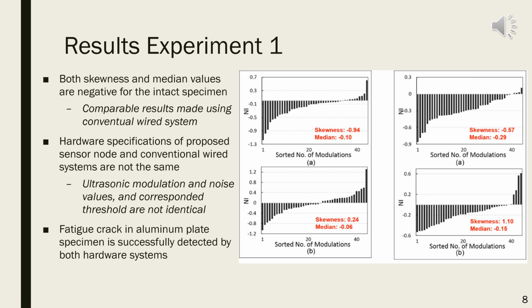Both the skewness and median values are negative for the intact specimen. Comparable results are obtained using the conventional wired systems, shown in the figure on the right. Hardware specifications of the proposed sensor node and conventional wired systems are not the same, so the ultrasonic modulation and noise values or corresponding thresholds are not identical. The fatigue crack in the aluminum plate specimen is successfully detected by both hardware systems. As we can see on the graphs on the right, both the stick and detect method and the conventional method predicted the fatigue cracks that were present.